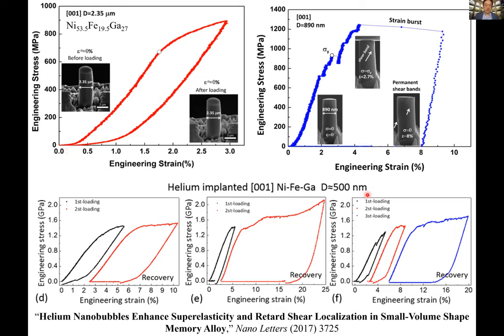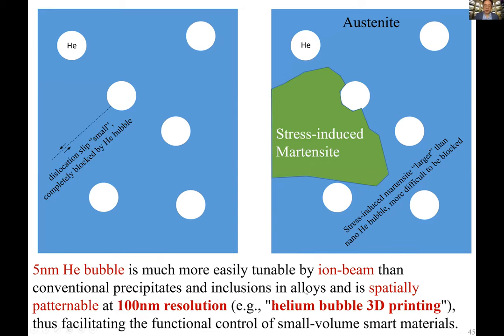What we found, however, is that when we implant the helium bubbles, we get back some of our recovery. This is quite interesting because it would allow us to pattern the mechanical behavior of a small structure by implanting helium. You can think of it as 3D printing of helium bubbles. We think these bubbles, as we demonstrated before, stop dislocation slip and stacking faults, but they cannot stop the bigger B2 to B19 prime phase transformations. So relatively speaking, these bubbles enhance the plasticity flow stress, but don't enhance the phase transformation stress as much.